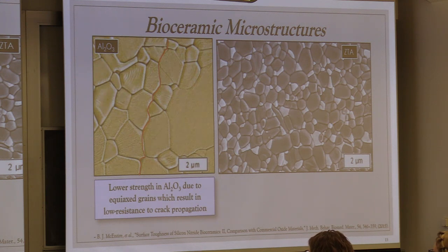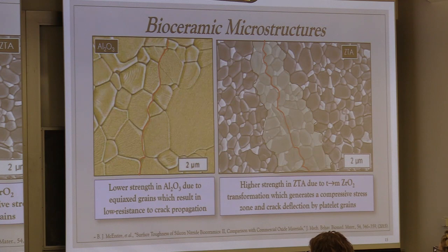And what's the unique thing about it? Well, it looks like it has equiax microstructure as well, but what happens when a crack propagates through it? As a crack propagates through it, it also follows basically grain boundaries, but in this case, as the crack propagates, it triggers a transformation in the zirconia grains around the crack that invokes a volume expansion of those grains from a tetragonal phase to a monoclinic phase of about 4%. And that volume expansion actually puts compression around the crack tip as it propagates. So it tries to hinder the crack from opening and moving by this compression method. So it has higher strength in ZTA because of this transformation that occurs in the material.